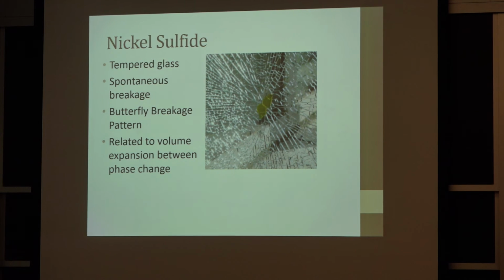To cause that spontaneous breakage, it relates to the volume expansion between the phase changes for the nickel sulfide. You have an alpha phase and a beta phase for the nickel sulfide inclusion. When it transforms between those two phases, you have volume change. If it's in the mid thickness, now you're putting tensile stresses into the glass as it expands, and glass doesn't work well under tensile stress. It can accommodate it to some point, but at some stress, it's just going to break.